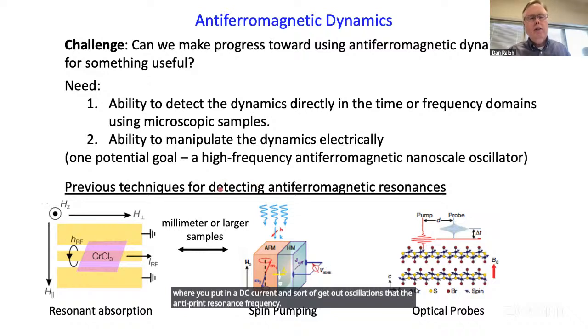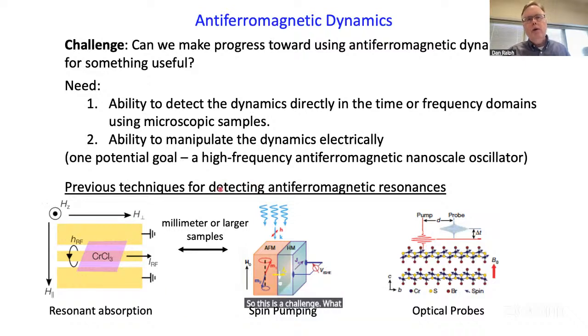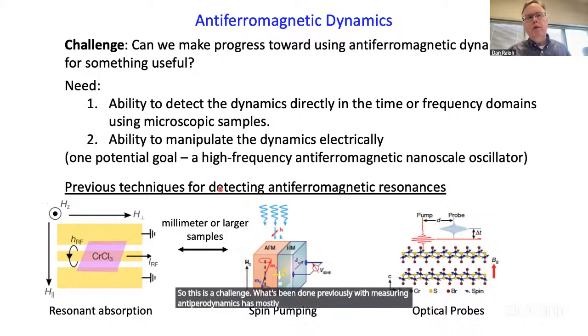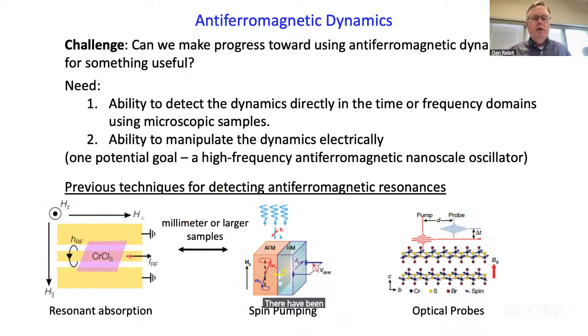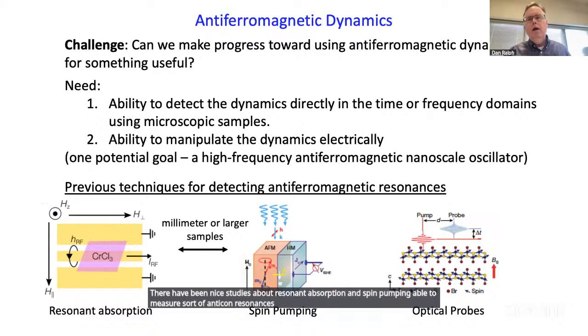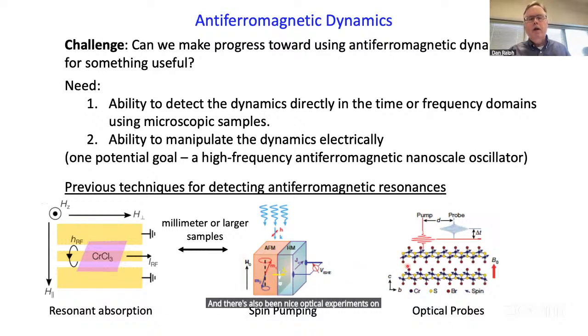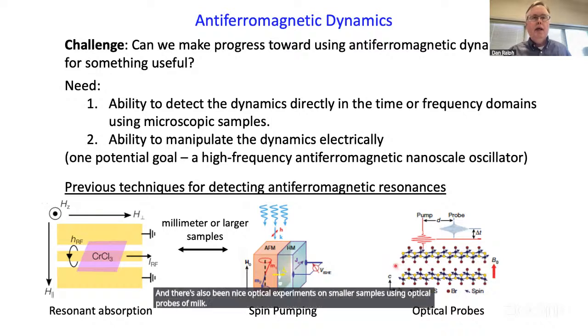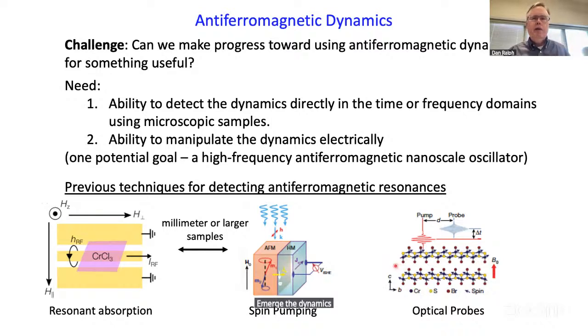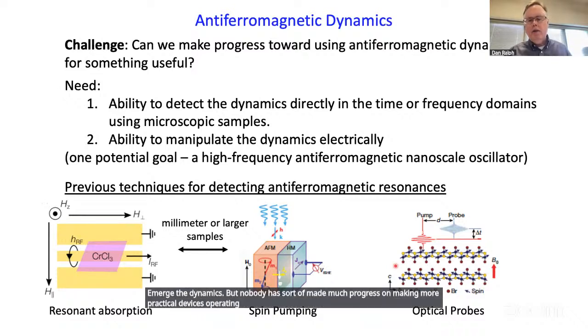So this is a challenge. What's been done previously with measuring antiferromagnetic dynamics has mostly been with very large samples, millimeter or larger samples. There have been nice studies about resonant absorption and spin pumping, able to measure antiferromagnetic resonances with those techniques. And there's also been nice optical experiments on smaller samples using optical probes of MOKE to measure the dynamics. But nobody made much progress on making more practical devices operating at the high frequency scales of the dynamics.